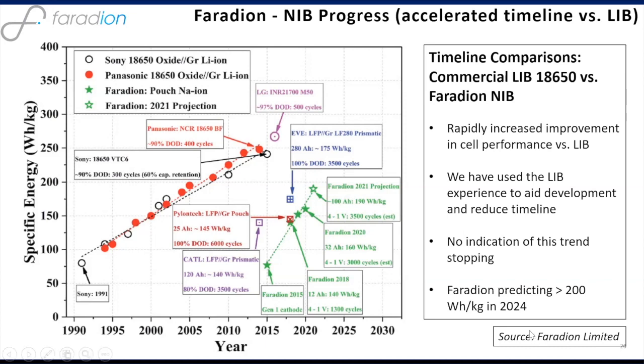Well, the green line down here is what's happened for NIB. Because we've all come within Faradion, we've already come from a lithium ion background, we've used our experience to aid the development and reduce the timeline. So we're running at a very accelerated time frame, and our current prototype cells are about 160 watt hours per kilogram, but we're predicting confidently that there's no indication that this trend of growth will stop, and that we should get to over 200 watt hours per kilogram in the next 2 years.